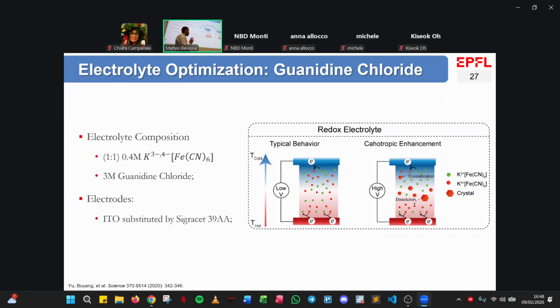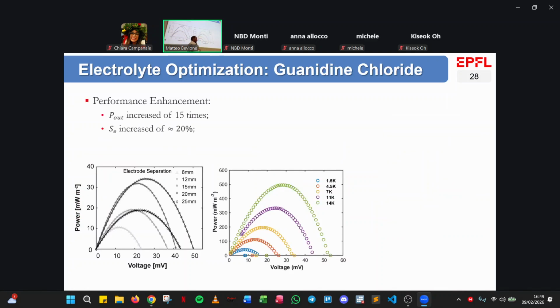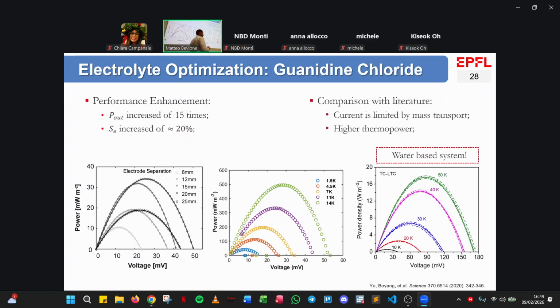And here in particular, what I did was changing the supporting electrolyte to a guanidine chloride component. This is fundamentally a chaotropic component that crystallizes one of the two redox species and allows you to get a better diffusion throughout the system. So for this, if you look just at the scale of these two graphs, we could improve the power 15 times, which is pretty nice. And especially comparing these gelled quasi-solid thermoelectrochemical cells, we got fundamentally the very same power performances as liquid devices.